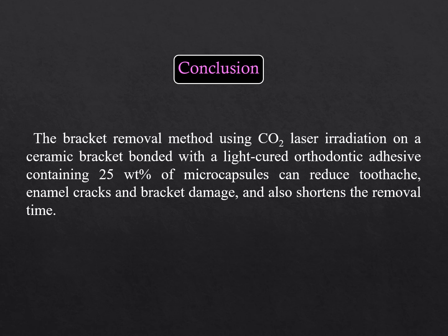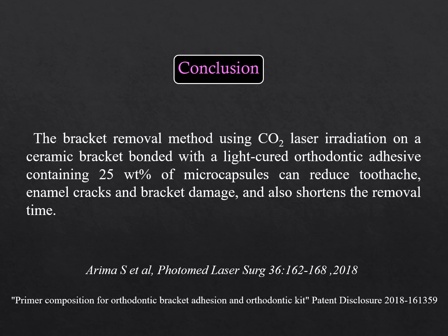In conclusion, it is most likely that the bracket removal method using CO2 laser irradiation on a ceramic bracket bonded with a light-cured orthodontic adhesive containing 25 weight percent of microcapsules can reduce toothache, enamel cracks, and bracket damage, and also shortens the removal time.